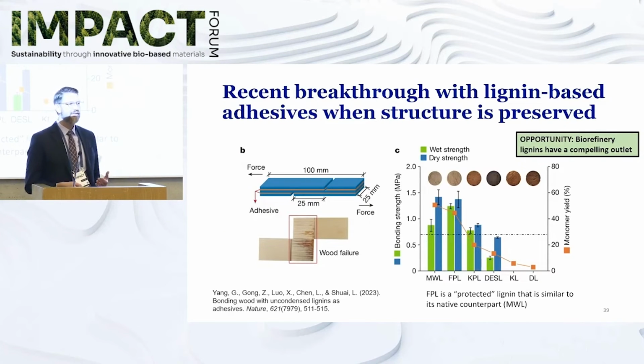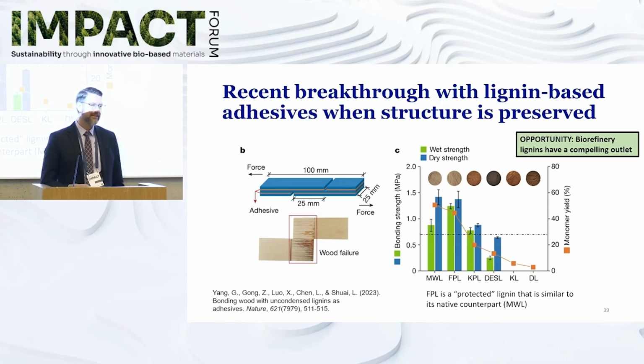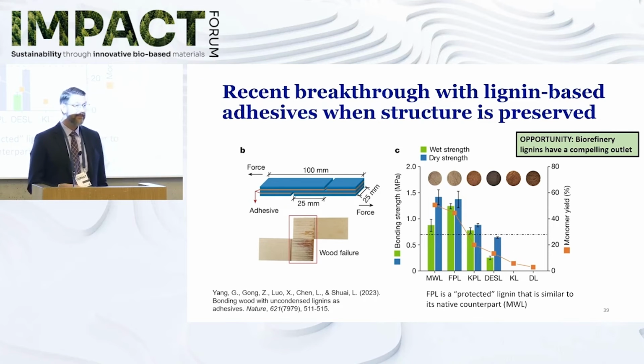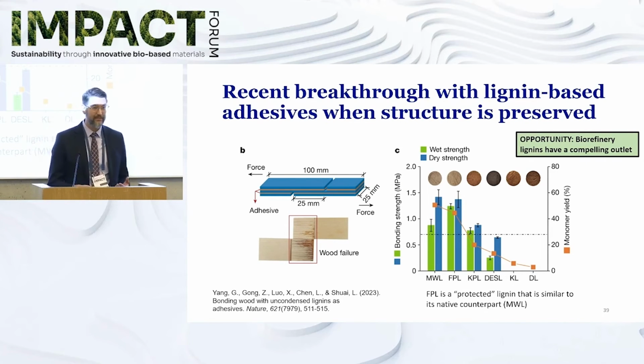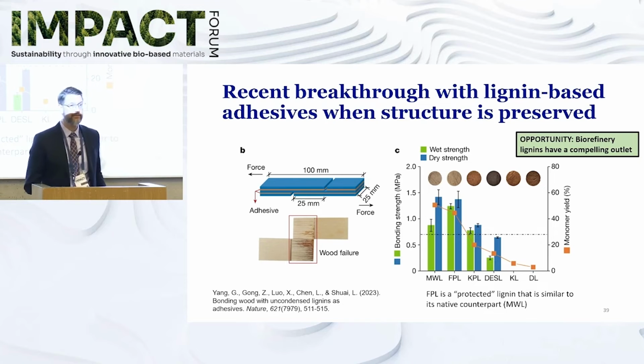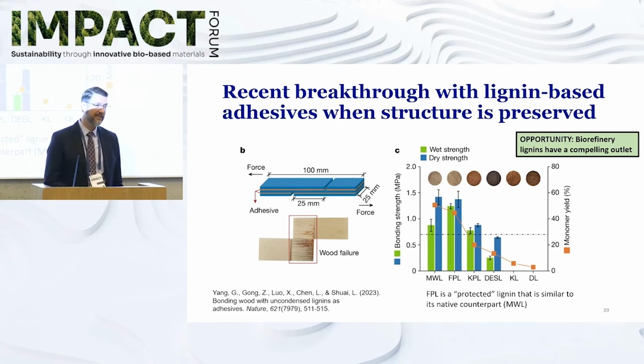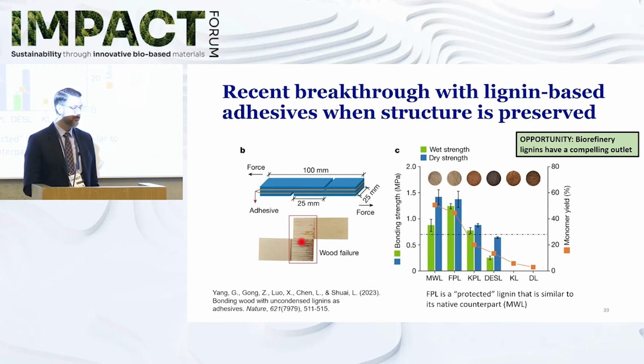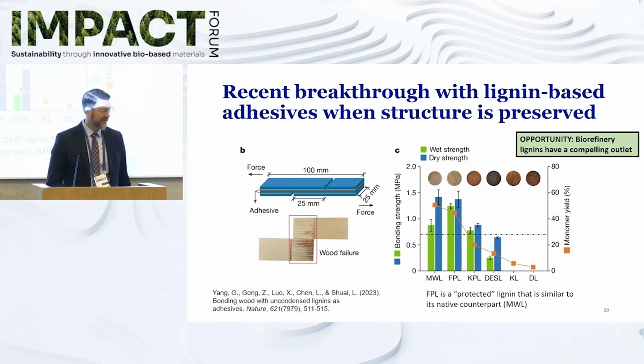Highlighting one of the kind of newer applications that have been developed for lignin, and so if we don't use kraft lignin but use a more native-like lignin, this actually gives you a picture of a piece of plywood that's been bonded together with only lignin, right? And so that's kind of incredible in terms of using lignin directly as an adhesive, and so it's a special biorefinery process that they use to protect the lignin when they isolate it, but then they can just coat it on the wood and they can cure it under heat, and that actually causes the lignin to cross-link together.